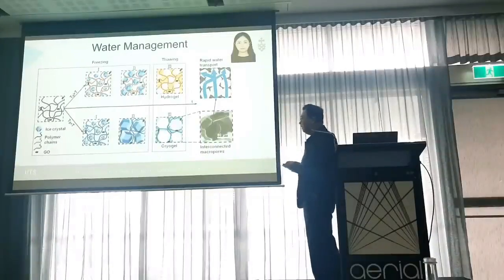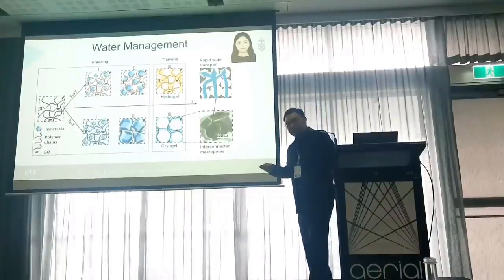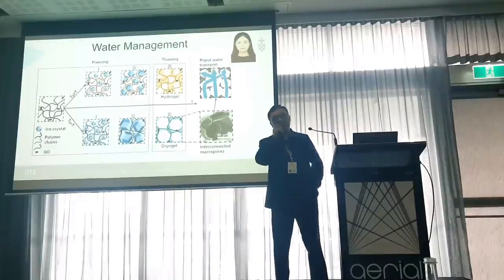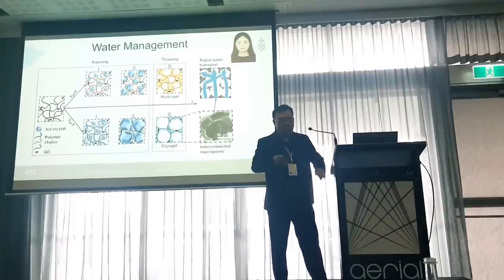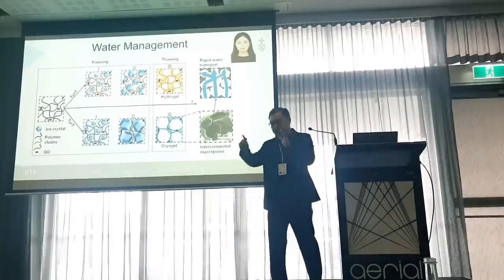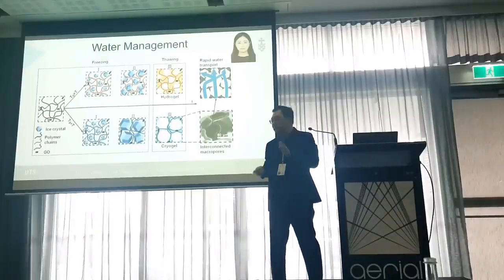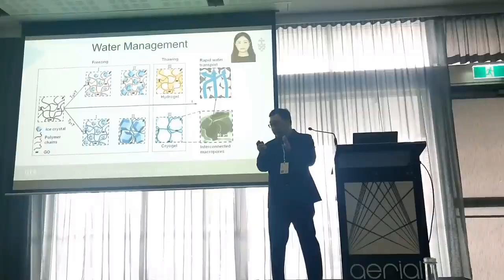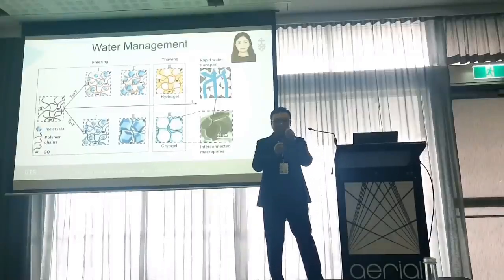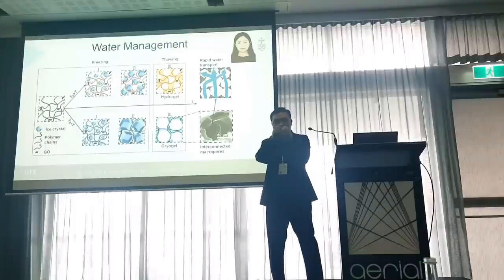So what's the reason? This result can be attributed to the difference in glass transition temperature between these raw materials. Specifically, PVA has a higher Tg, about 50 degrees centigrade. Therefore, in the freezing process that is conducted at minus 18 degrees centigrade, the polymer chains lack flexibility. So in the hydrogels, the growth of the water crystals was limited.